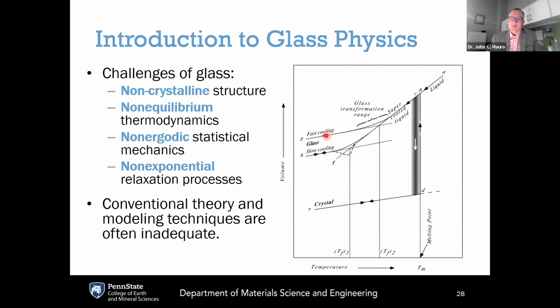So you get a material that for practical purposes behaves like a solid. Mechanically, it behaves like a solid, it breaks like a solid, but it has the structure of a supercooled liquid. And that is what we all know and love as a glass. And glass is a thermodynamically unstable system. It is continually trying to relax towards the supercooled liquid, and the supercooled liquid is in turn metastable with respect to the crystal. So if you wait an infinite amount of time, the glass is going to relax towards the supercooled liquid and then undergo a phase transition to crystallize.